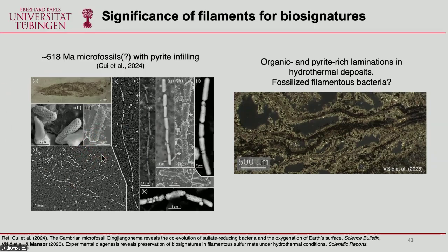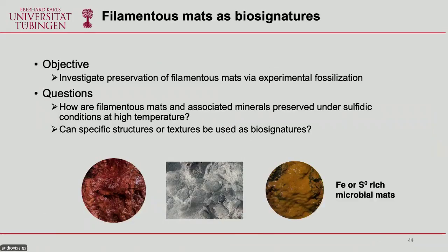But what they suggested, they go even a step further. They suggested that these are actually fossils of sulfate-reducing bacteria. And I was a bit skeptical when I saw this because I wasn't sure on how exactly this can happen. And we also see a lot of similar structures in hydrothermal deposits, hydrothermal vents. We see these organic laminations that are fully coated with pyrite. And could this be fossilized filamentous bacteria? And so we wanted to test this in the lab. We used this approach called experimental diagenesis or experimental fossilization. We had some questions whether the filamentous mats and associated minerals can be preserved under sulfidic conditions at high temperature. And can specific structures or textures be used as biosignatures?